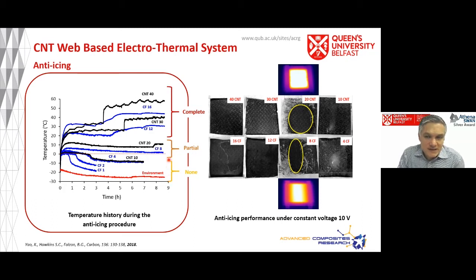We don't prevent the buildup of ice. If we then increase the thickness, we increase the heat going into the system, we get some partial melting. And then you can see how we can get complete melting once your number of carbon nanotube web layers is about 30. In fact, it's more than you need. You get complete evaporation of the water. That's why you get that jump in temperature.